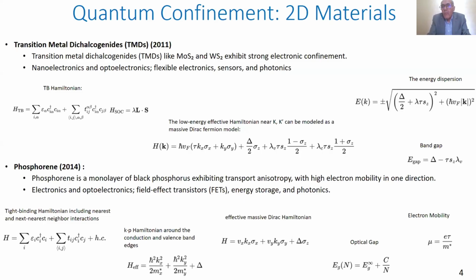The simplest way to describe this material is also by tight binding Hamiltonian. In this case, on-site atom energy and hopping terms are present in this Hamiltonian, and we can also simplify this Hamiltonian by introducing effective mass Dirac Hamiltonian with the gap term. In this case, the optical gap is no more zero like for graphene, but it is a semiconductor, and the gap increases with decreasing the number of layers in the thin films of phosphorene.